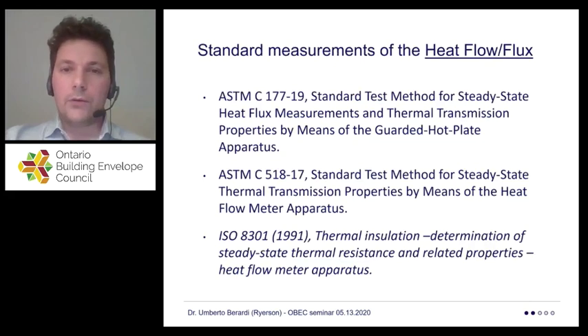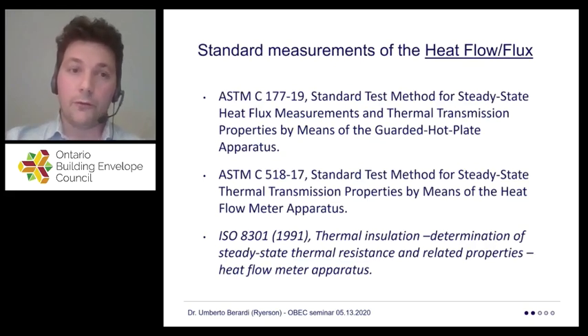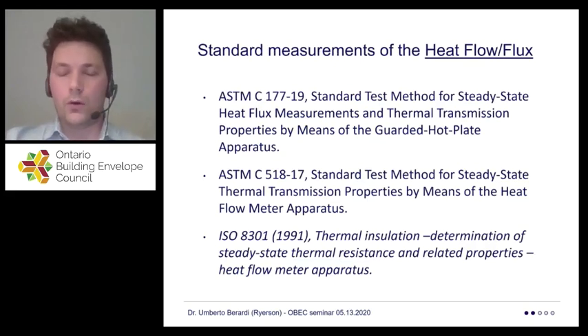So in reality, all the heat flow or heat flux methods, depending on whether you're using a guarded hot plate or a heat flow meter, or even international standard 8301 that was first approved in 1991 and has been recently reapproved in 2019, all these measurements that are used to populate technical sheets give you values of thermal conductivity at the ambient temperature, which is probably not important for enclosure design, or needed for air conditioning design.